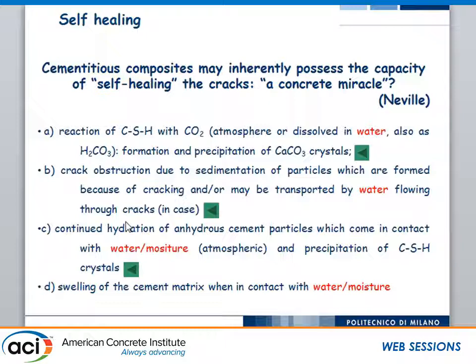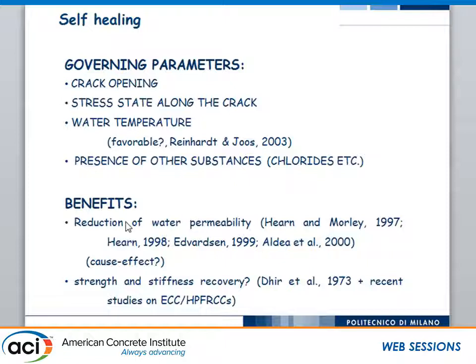Well, the problem is quite complicated because there are several variables governing it: the level of crack opening, the presence of sustained stress across the crack, so the combination of static and environmental loading, the temperature of the water, the presence of other substances such as for instance with salt water that you were testing. As a matter of fact, a lot of studies have been done measuring the reduction of water permeability. But in this kind of experimental test, what do we have?